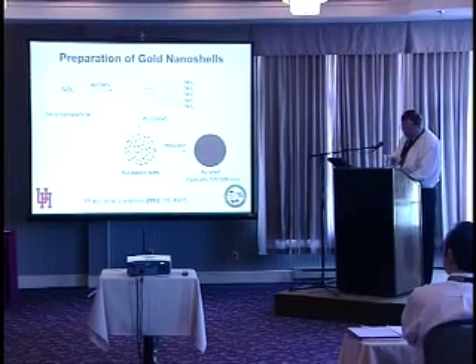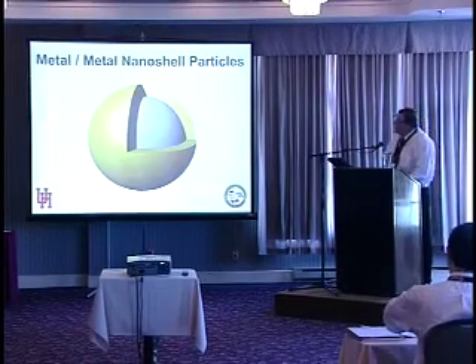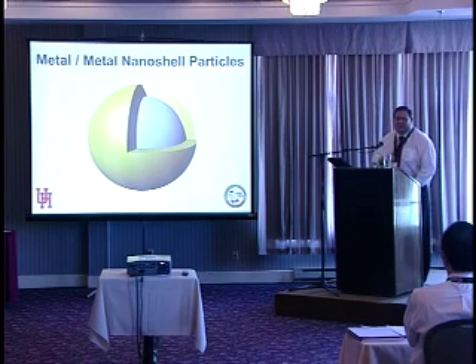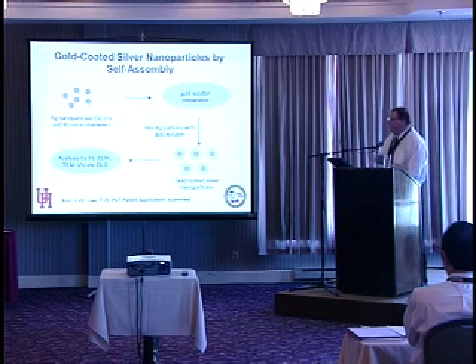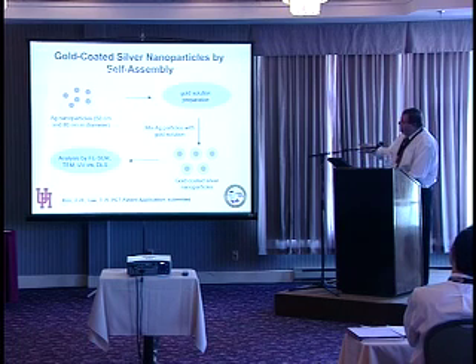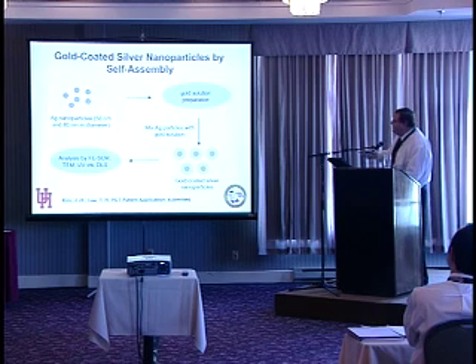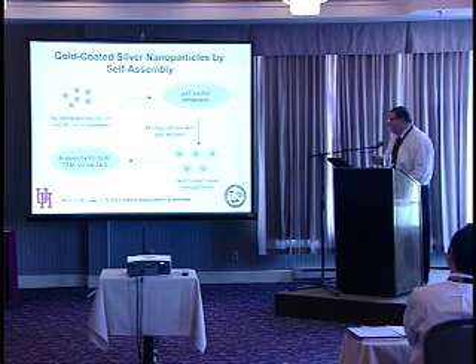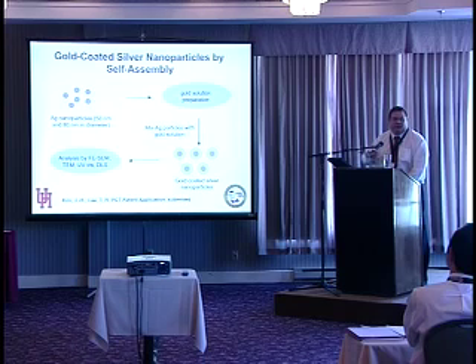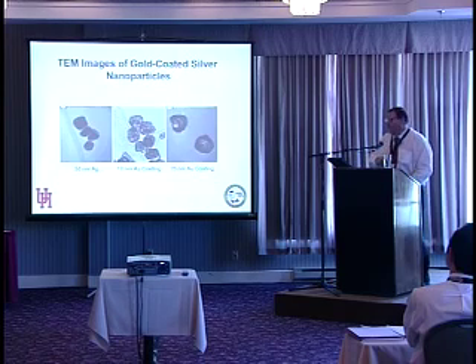And so to address the synthesis problem, we have developed a new type of nanoparticle that it turns out to be much easier to make, but has a lot of the same properties. For example, we call them metal-metal nanoshells. We can take a silver core particle and just pour it into a specific gold solution, and the gold shell will immediately grow around the silver nanoparticle core. So it's really a two-step process. You make the silver core and treat it with the gold solution, and you've got your nanoshell.